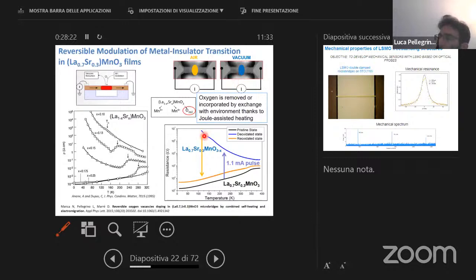So you can go back by heating the sample in oxygen atmosphere, and you go back here, and you almost recover the original ferromagnetic state. So this is kind of an example of how you can use particular materials that you can tune reversibly, and not only the resistance, but even the magnetic property, structural properties by changing the conditions.